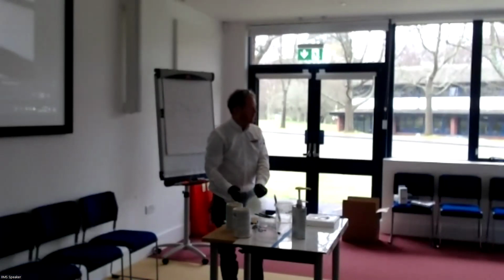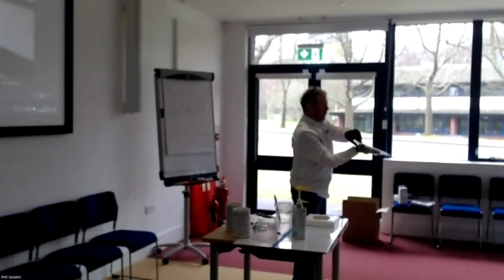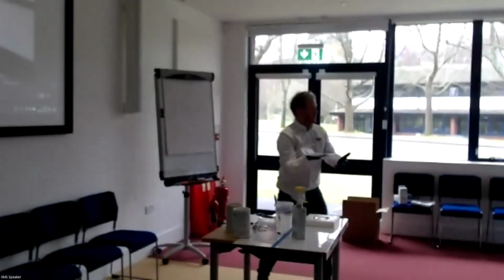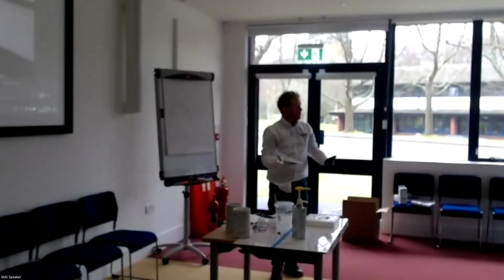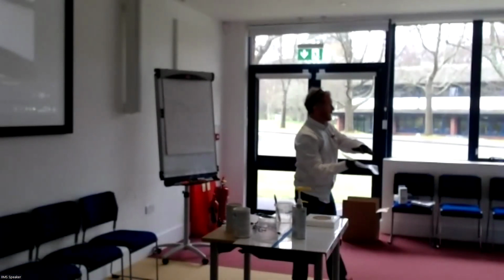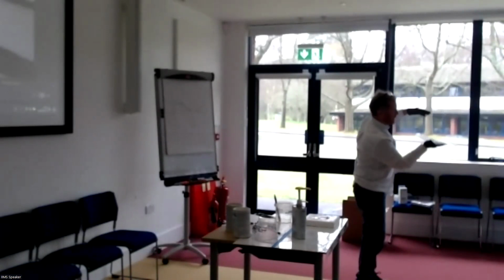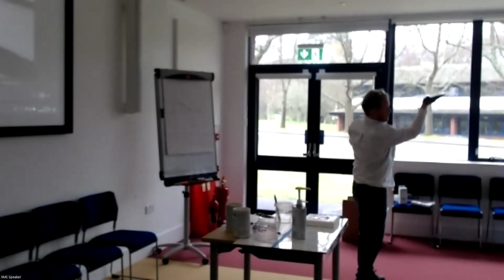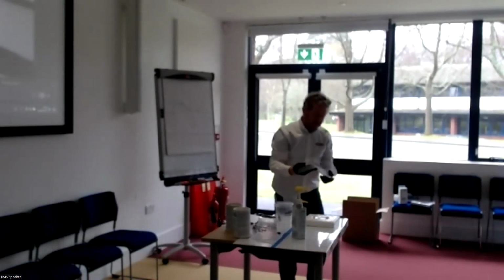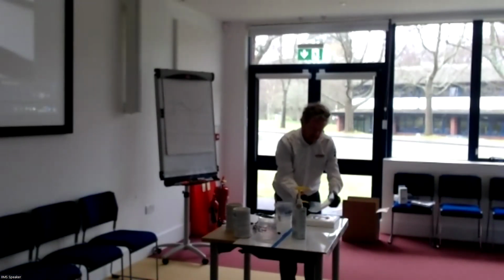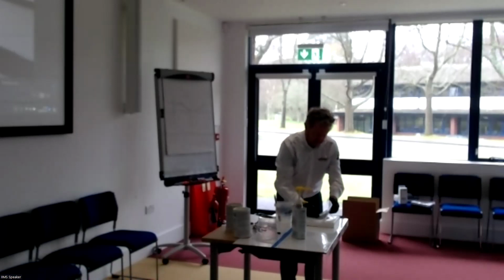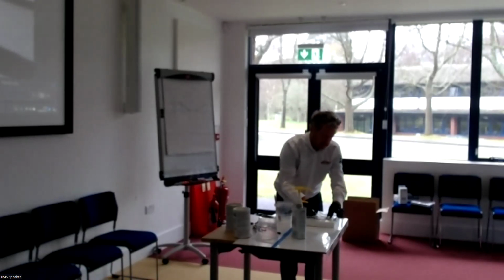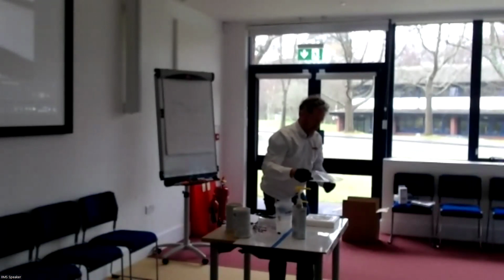So you see, that's actually incredibly quick. And of course, this work could be done inside the boat in the dry, with another piece of plastic over it, taken to the outside with a cover underneath the boat, and then applied. And of course, it can be applied upside down. And the trick to working it upside down is to very carefully apply it and then roll the air out from underneath, just with your hands, just like that. And then just get rid of the plastic, and your job is nearly done.